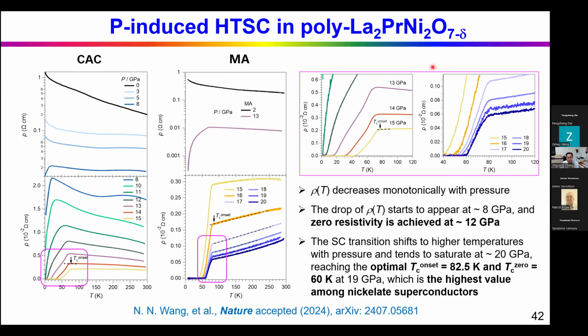There's an enlarged figure here. You can see at about 19 gigapascal, the TC0 can reach about 60 Kelvin. So this is the highest value for the nickelate superconductors reported so far.